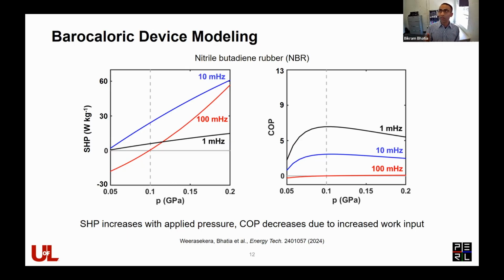So it's pretty substantial. In elastomers, the hysteresis is relatively low. The fatigue life is decent, although the fatigue life has been tested for elastomers for a wide variety of applications, not necessarily for barocaloric, but the performance is decent and the hysteresis is relatively low compared to materials that have order-disorder transition. That being said, there are a lot of chemists and material scientists who are working on reducing this hysteresis. They think it has to do with the hydrogen bonds being broken and reformed as you apply pressure. So there are reports of lower hysteresis materials being reported almost every other week these days. Got it. Thank you.